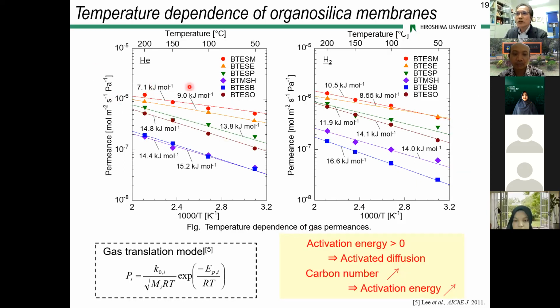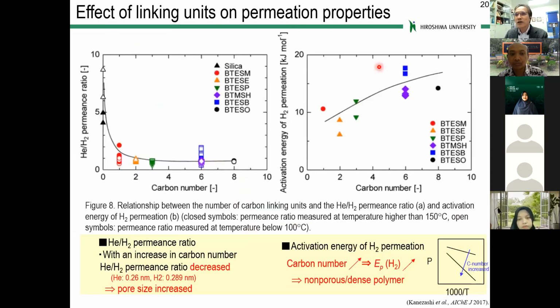Now this slide shows the temperature dependence of the organosilica membranes. In the case of helium and hydrogen, there is almost a similar curve trend. By using a different linking unit, methane here, ethane, propane, hexane, and octane here, and benzene is expressed with a square here. Then we get the activation energy for each membrane and summarize it this way. So this summarizes the effect of the linking unit on the permeation properties.